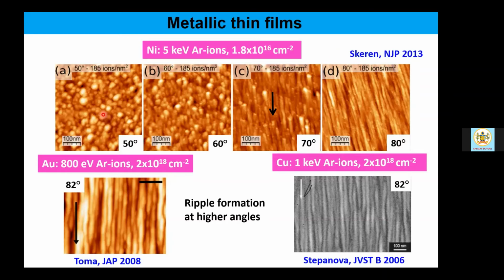And formation of small nanodot-like objects turn into ripple patterns from 50 degree to 70 degree incident angle, and very mature ripples are formed, where the ion projection is parallel to the ripple orientation at an incident angle of 80 degree.